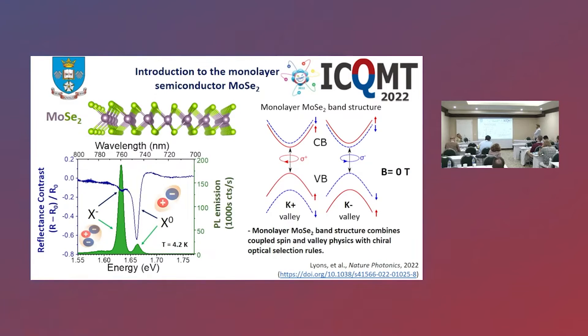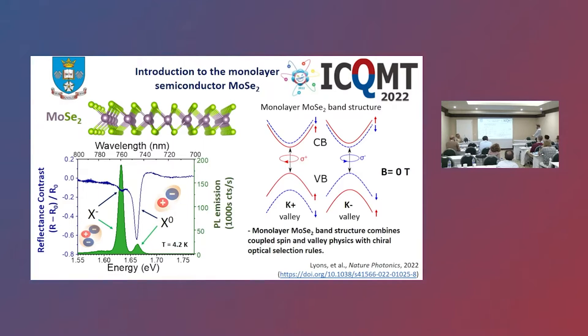The material I would like to present is molybdenum diselenide (MoSe2). At low temperature, we can see it has highly excitonic optical properties, and the neutral exciton has a very large oscillator strength, while the trion has a relatively smaller one. What's quite interesting about MoSe2 is that the band structure combines coupled spin and valley physics with chiral optical selection rules, meaning you can optically address one valley or the other through circular polarization — you address K-plus with sigma-plus and vice versa.